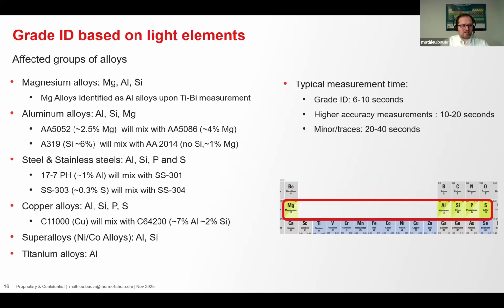That's, for example, grades that differ only in their magnesium content, such as 5052 and 5086 grades, or to differentiate numerous cast aluminum grades, such as A319, from some wrought aluminum grades based on the difference in silicon and magnesium content. There are also a few stainless steel grades that need the measurement of light elements, such as the 17-7 precipitation hardening grade that contains about 1% of aluminum, which may be mixed up with 301 grade if light elements are not measured.